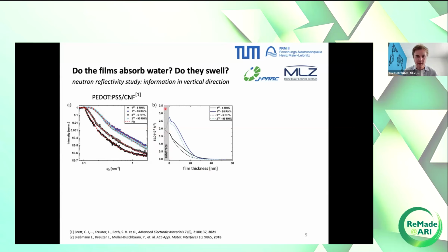You would have here the substrate and then on top the film, and at some point the film-air interface, polymer-air interface. And what you see immediately is that we definitely have changes in the thin film structure, vertical thin film structure, so Qz. From black to blue, or from low to high humidity, something is happening. The SLD is increasing. And we attribute this to an absorption of water.